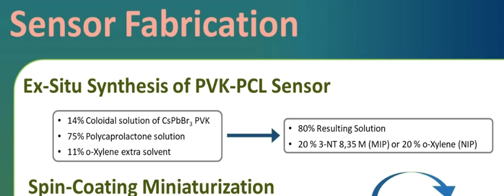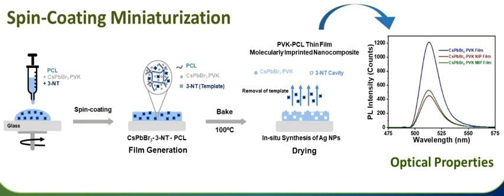A common strategy used for the fabrication of perovskite polymer nanocomposite films is to use ex situ methods. In this approach, nanoparticles are synthesized by wet chemistry as a colloidal solution and then dispersed into a polymer solution, which is finally spin-coated to form a thin film, and the holes are formed when the bake process takes place. As a result, homogeneous and transparent thin films of the perovskite polycaprolactone nanocomposite were successfully generated.